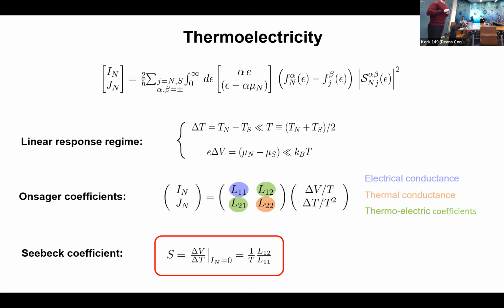An important figure of merit for thermoelectricity is the so-called Seebeck coefficient. This Seebeck coefficient is just defined as the ratio between the induced thermal voltage delta V divided by the applied thermal gradient delta T when the charge current through the system is equal to 0. And it's very easy to show that this is related to the Onsager coefficients in the linear response regime by this relation, L12 over L11 times 1 over T.